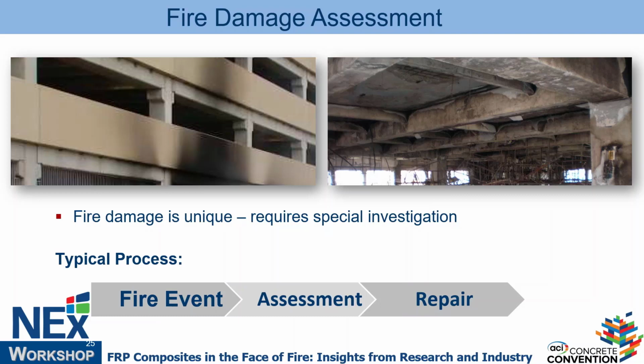So some basic things. You can do hammer sounding to see how far the delamination extended into the concrete, right? Because sometimes the concrete looks good, but due to expansion of steel reinforcement, you get separation, right? You can do drill probe, where you basically drill vertically, and when you start hitting resistance, that tells you the depth of the damaged concrete that needs to be chipped and removed.